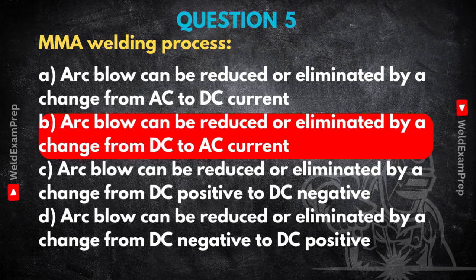And we dove into MMA power sources, understanding the constant current principle, how arc length affects voltage. Voltage drops when the arc shortens. And finally, tackling arc blow by understanding why switching from DC to AC is often the best fix. Fighting those magnetic fields. It really shows how all these pieces fit together to ensure you get a sound, reliable weld in the end. It absolutely does. And hopefully this dive highlights that it's not just about memorizing answers. It's the understanding behind the answers that truly matters. Knowing the why gives you the ability to problem solve, to adapt, to make informed decisions out in the field. That's far more valuable. Couldn't agree more.